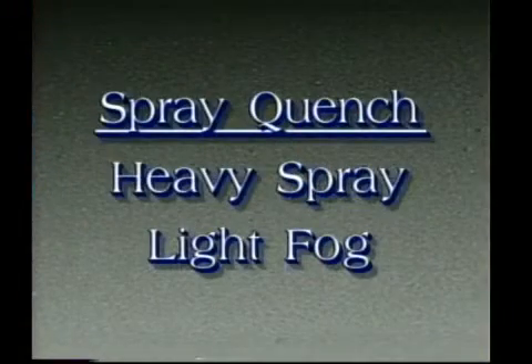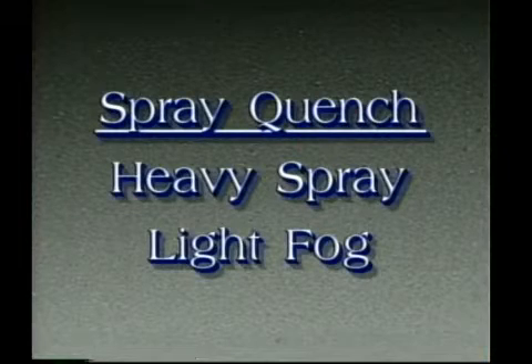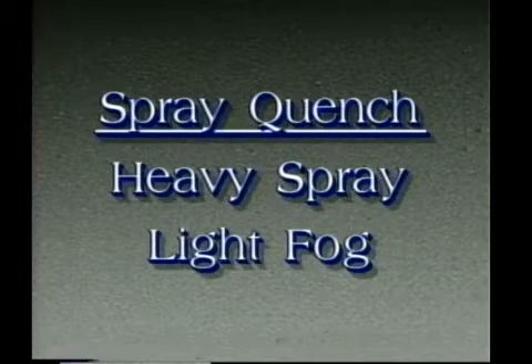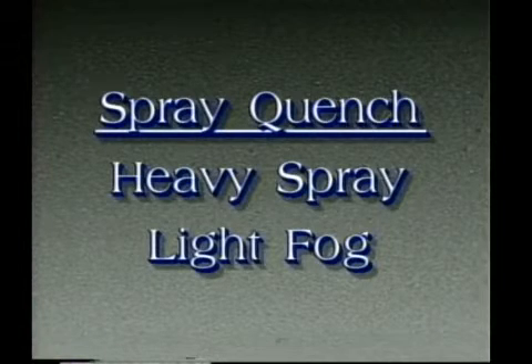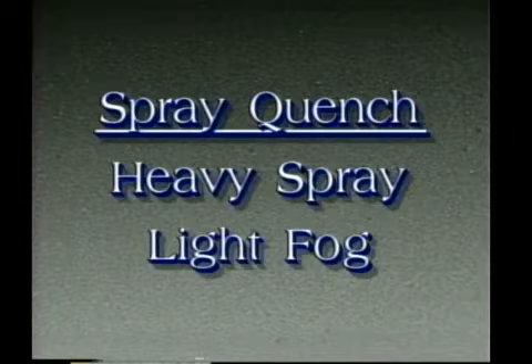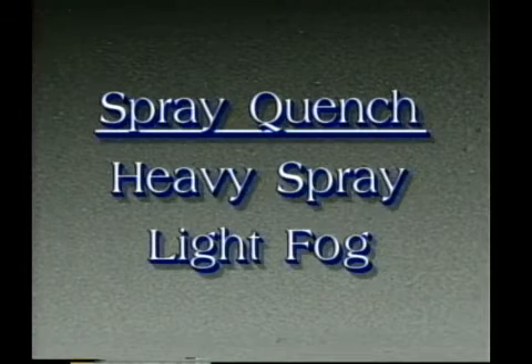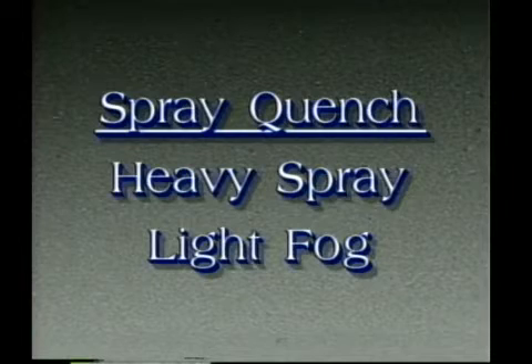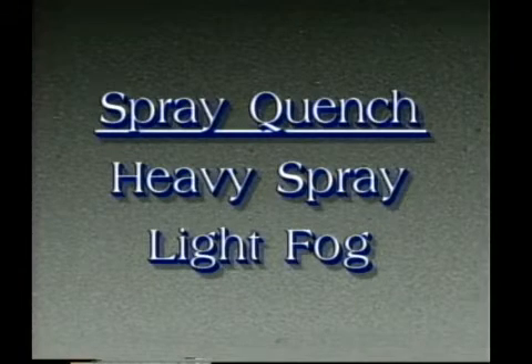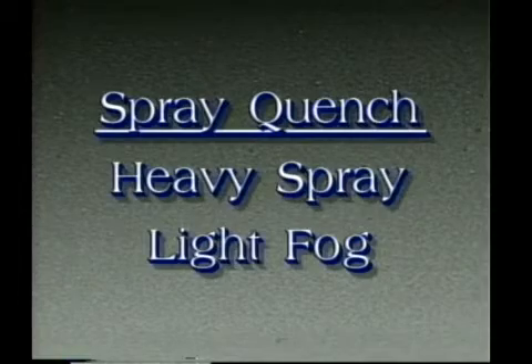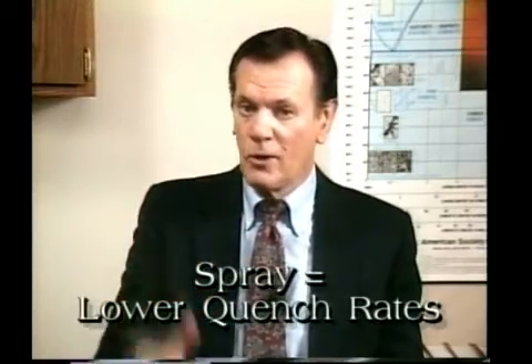Some distortion problems can be solved by using spray quenching techniques. The commercial application of spray techniques in aluminum alloys varies from the use of a heavy volume of a high-pressure spray to that of a light fog or mist. Thus, the quenching characteristics of a particular spray quench facility can vary significantly depending upon the design and characteristics of the equipment being used. When using spray quenching techniques, care must be taken to ensure that the procedure is adequate for achieving the required properties in all parts being heat treated. The use of spray quenching normally results in much lower quench rates when compared to cold water immersion quenching.